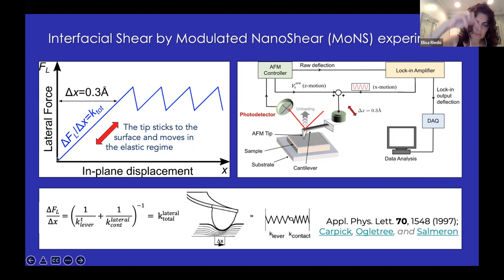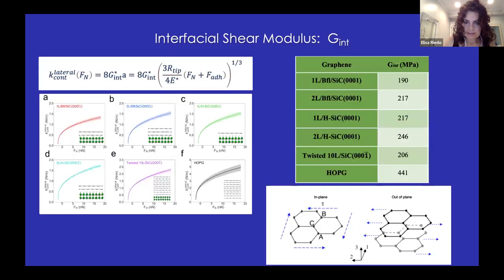So we go in contact, we apply a certain load, as I said before, quite a small load, but enough to keep the contact. And then we move essentially along this line here for some displacement that is smaller than one angstrom. I think it's 0.3 angstrom. Okay, next, we obtain the lateral contact stiffness as a function of the load. And this contact stiffness based on contact mechanics is given by 8 times the interfacial effective shear modulus times A, where A is the contact radius.